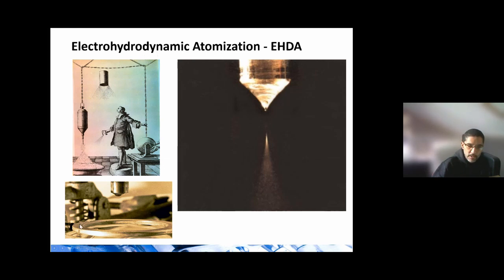If you get a nozzle and you put a metallic piece close to it and apply a very strong potential difference between them, in the order of kilovolts, the electric field will change your spherical meniscus into a conical meniscus, from where a jet emerges and breaks up into droplets, very small ones. You can see from this picture that they are much smaller than the nozzle diameter itself, which makes this technology very interesting because, for example, with a 1 millimeter nozzle, I can make 1,000 times, 10,000 times smaller droplets. So I can do a 1 micrometer droplet.